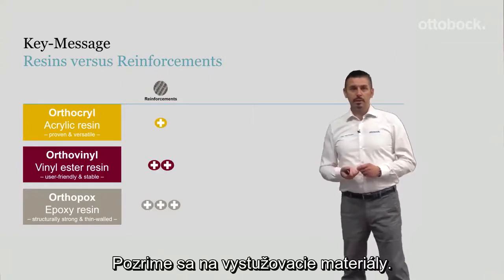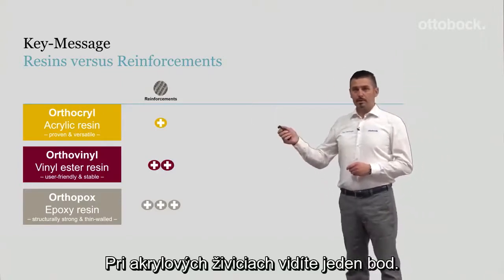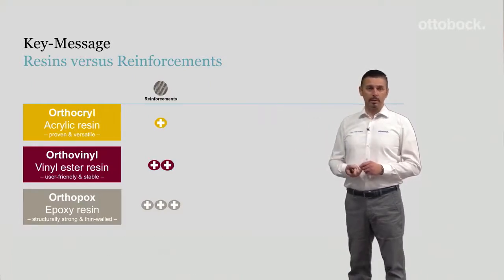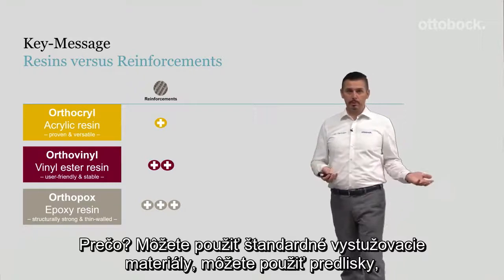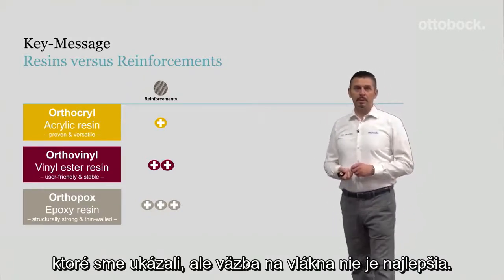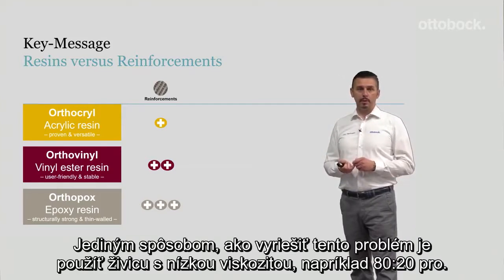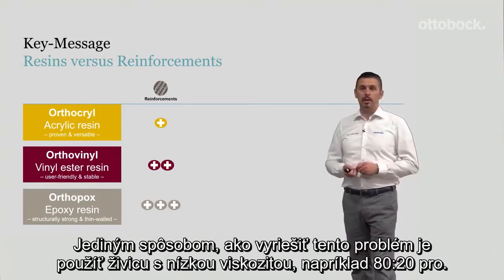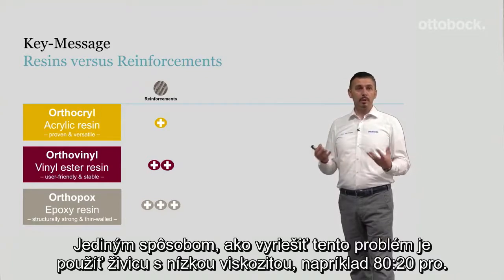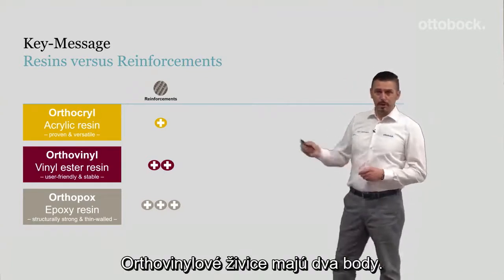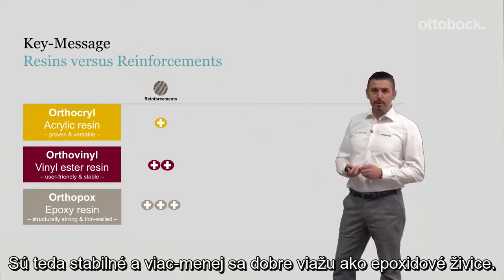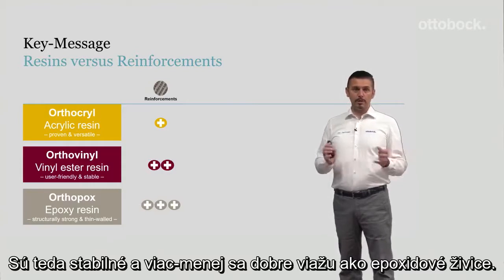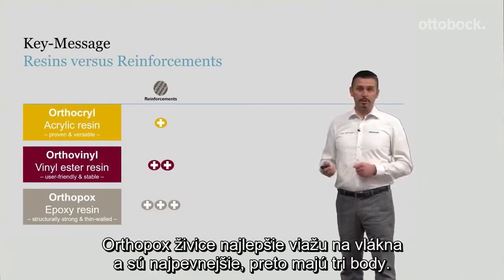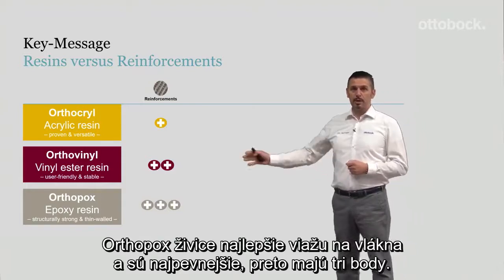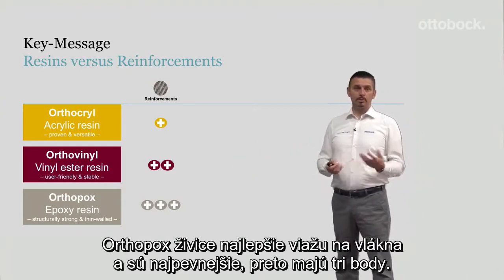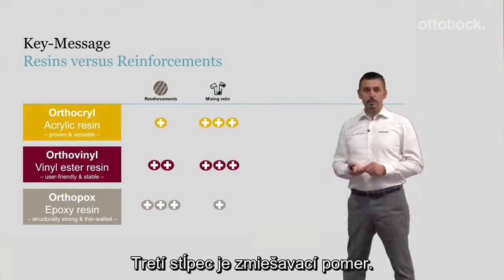Let's have a look at the reinforcement materials. You see 1 dot for the acrylic resins. Why? You can use standard reinforcement materials, you can use the preforms that we have shown, but the bonding to the fibers is not the best. The only way to solve this challenge is to use a resin with a low viscosity, for example the 80:20 Pro. The orthovinyl resin has 2 points, so it's stable and has a more or less good bonding like the epoxy resins. But the best bonding to the fibers and the highest strengths have the Ottobock resin systems, that's why 3 dots.